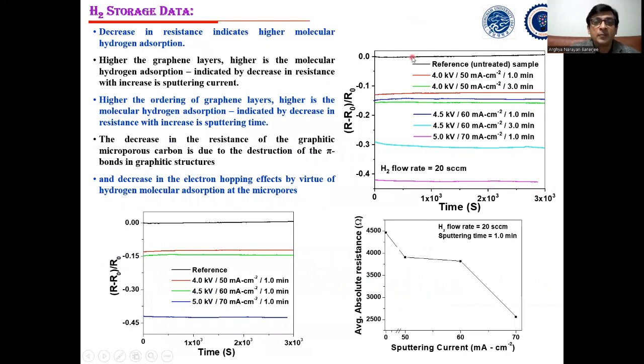Now we did the hydrogen storage testing of this physisorption material. For that, we used differential resistance measurement. What we did is put our device into a hydrogen flow system, flow hydrogen mixed with some nitrogen, and test the resistance in the presence and in the absence of hydrogen.